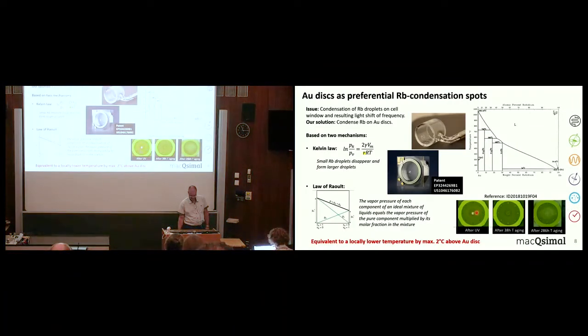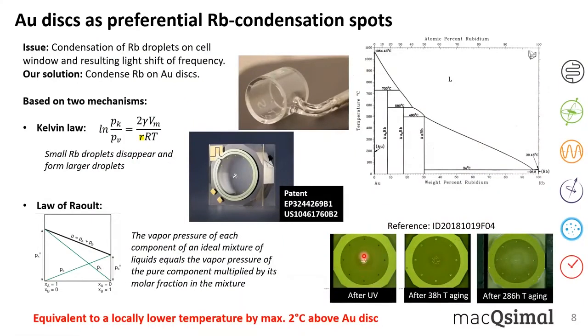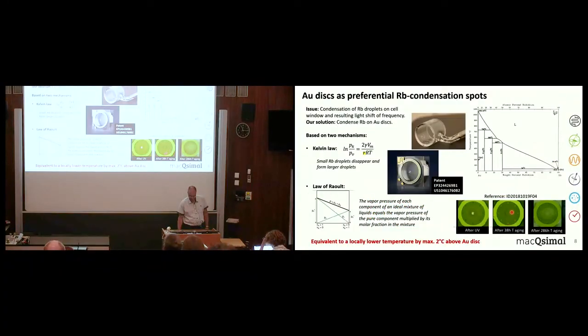We have here a vapor cell just right after UV decomposition with the rubidium droplets sitting in the center of the glass. You see also in black here the dots around, which are the gold discs seen from behind. And now, as you do a thermal aging, 38 hours later, almost all the rubidium in the center has disappeared, but you see that it went onto the gold disc and goes over the gold disc, so it's a little bit bigger than the gold disc itself. And if you continue this process, after 286 hours there is almost no rubidium left on the cell window, and all the rubidium is now fixed on these gold discs.